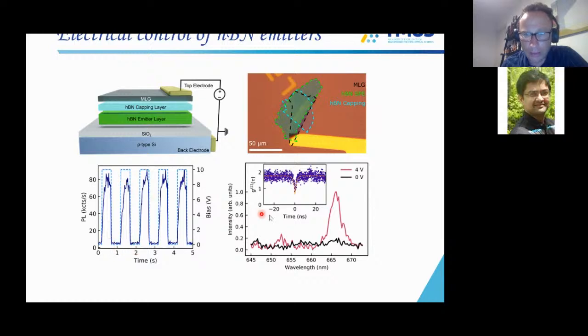And actually, you start inducing emitters. Okay, so this is not electroluminescence. The laser is always on. With the laser on at 0 volts, you see no emission. But with the laser on at 4 volts, you start seeing a very strong emission. And of course, it's a single photon source.